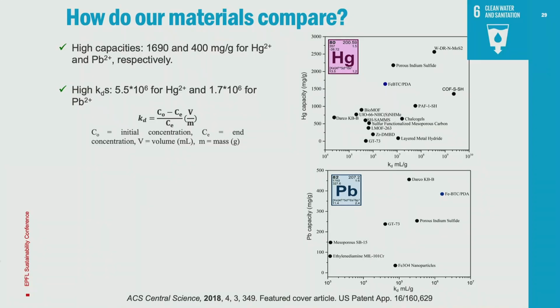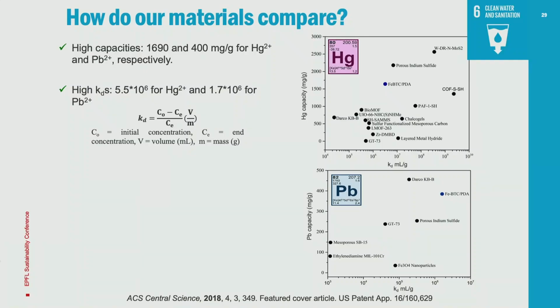So then we began to compare our materials in the literature. We found that how much they can absorb, how much they can take up is really nice. The KD is just the affinity. What is the affinity of the material towards a given metal? It's very high compared to other materials. Here's our material. You can see that in the case of lead, it had the highest affinity reported to date and one of the highest capacities as well.